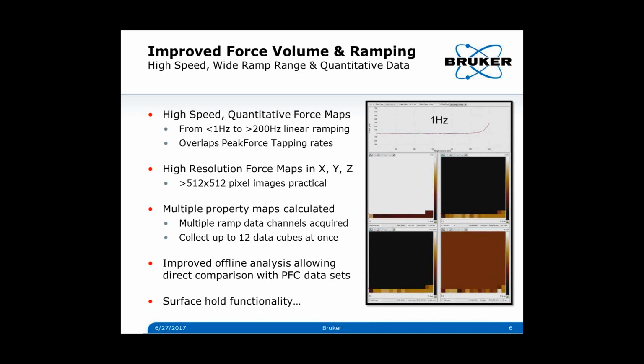Now, force volume has actually been significantly improved in the last few years. Here's some 1 hertz ramping, which would have been very typical a couple of years ago. We like to call our faster version of this fast force volume. And it allows us to go up to over 200 hertz in linear ramping. Here's 150 hertz. And that allows us to overlap the peak force tapping or peak force QNM rates.